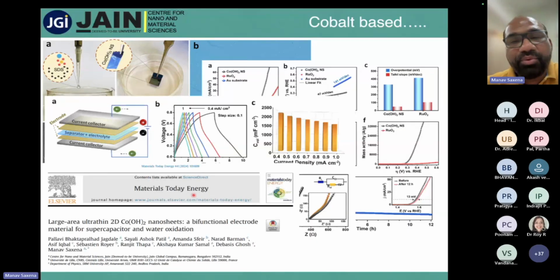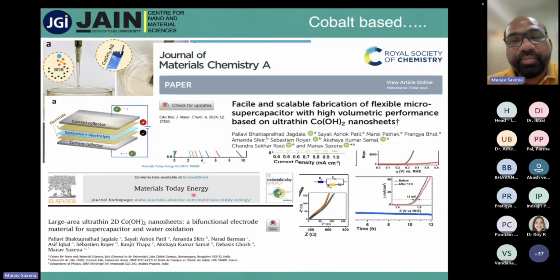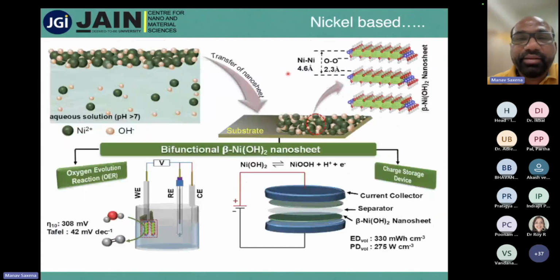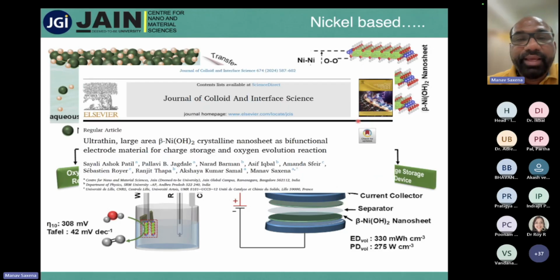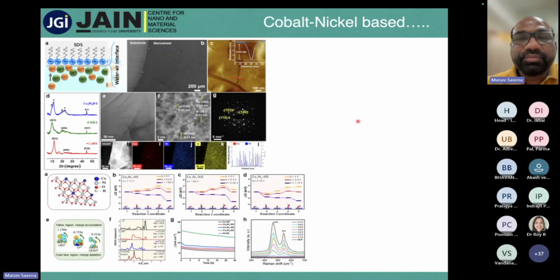Now, when we are working on cobalt, is it possible with nickel also? This cobalt work we also published recently in 2024 in JMC A, where we made the flexible micro supercapacitor. For the nickel based compound, we found the same technique works, where in an aqueous solution at pH 7 we make a large area thin film, and we published it in the Journal of Colloid and Interface Science.